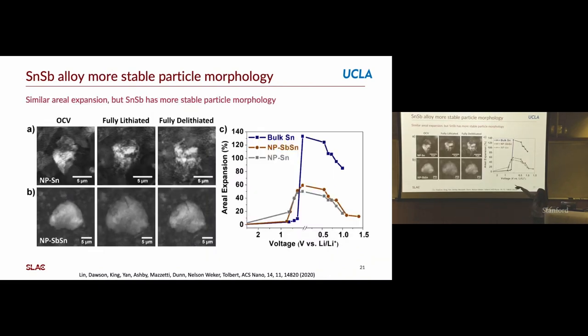On top is just a different nanoporous tin. On the bottom is the nanoporous tin antimony. And here are the three plots of areal expansion. This is averaged over many particles. And you can see that bulk expansion, the burst expansion from the bulk tin, but the nanoporous materials both follow the same trend. So they look on areal expansion to be the same, but you can see the nanoporous antimony and tin together preserve the shape, the overall micron-sized particle.